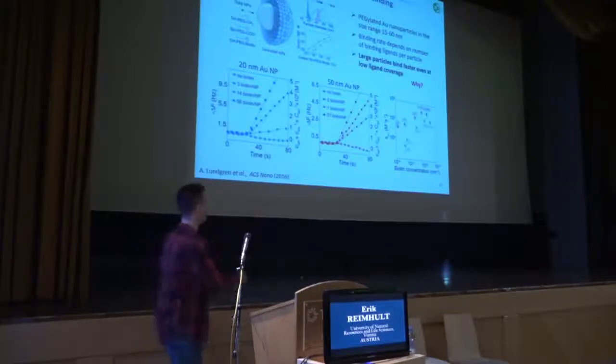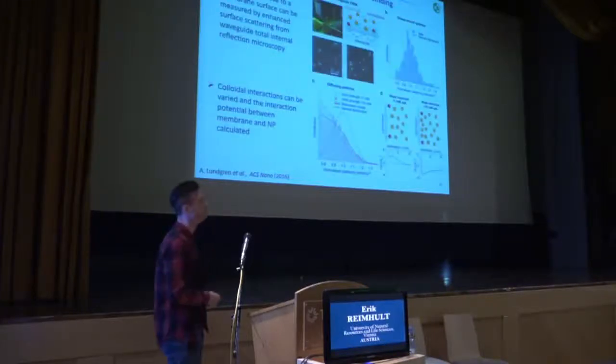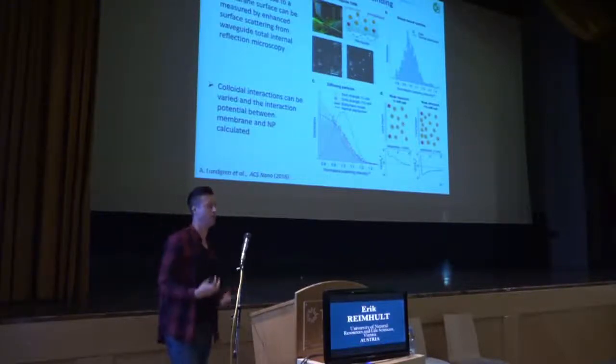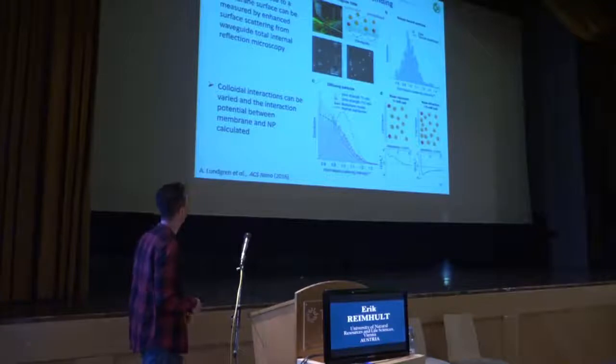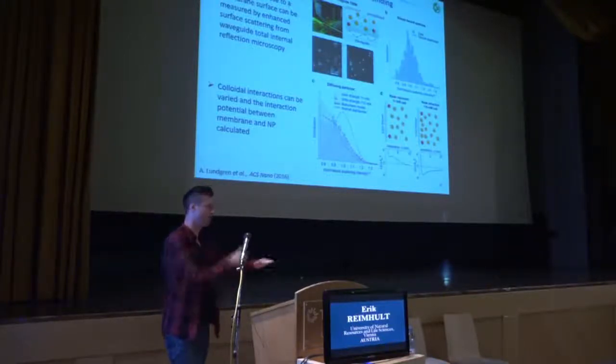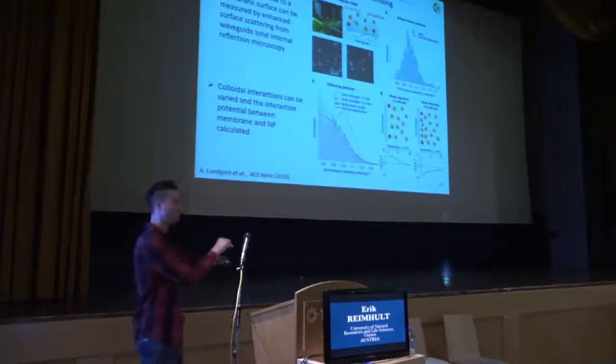If you have the same biotin density from the two particle shells, we should see these curves end up in one line and not in two, depending on size. So obviously this means we don't have the proper limitation. What can this depend on? Well, it can depend on that the particles are actually interacting with the surface that they try to bind to through non-specific forces, like van der Waals and double-layer forces.